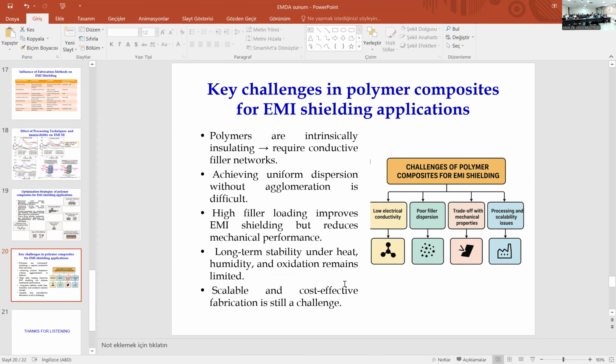Although increasing the filler loading can enhance the shielding effectiveness, it often leads to reduced mechanical flexibility and poorer processability. In addition, polymer composites may suffer from limited long-term stability, such as heat, humidity, or oxidation. They degrade their electrical performance and also affect EMI shielding performance. Finally, developing fabrication methods that are both scalable and cost-effective remains a significant challenge for widespread industrial adoption.